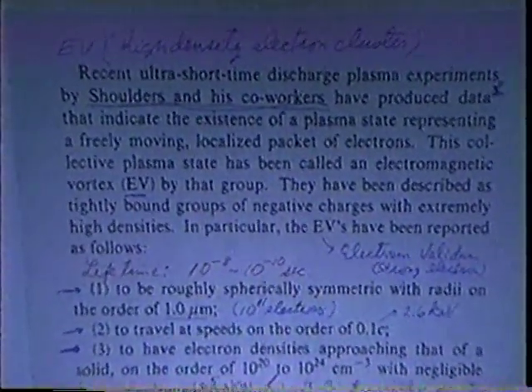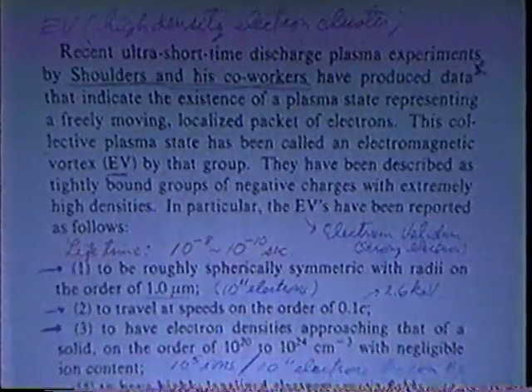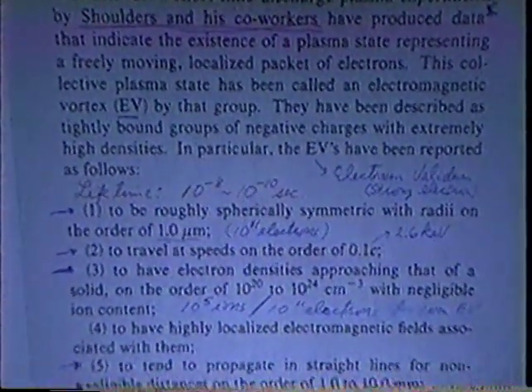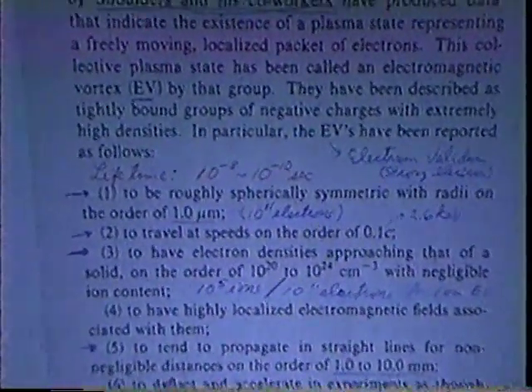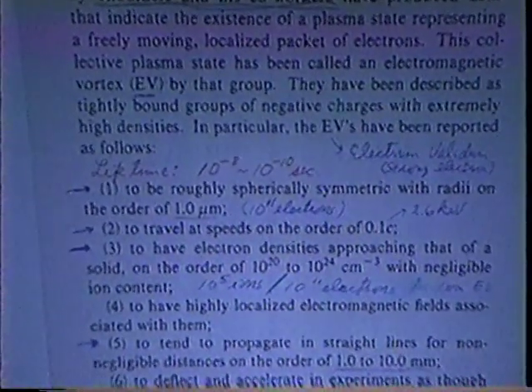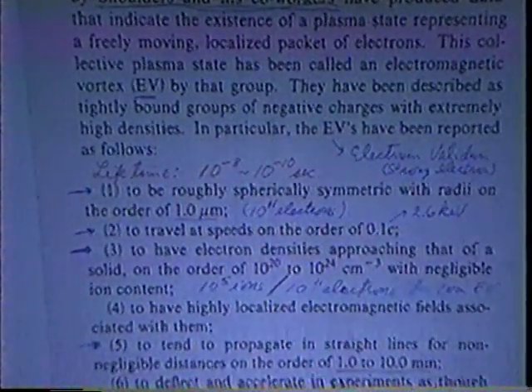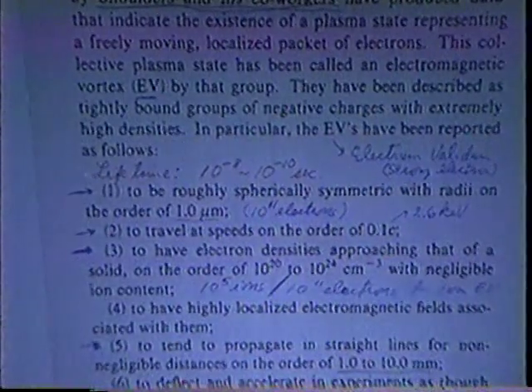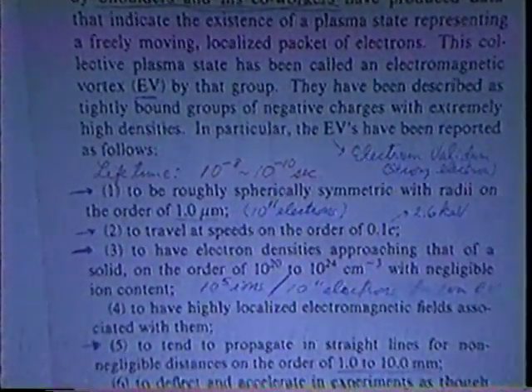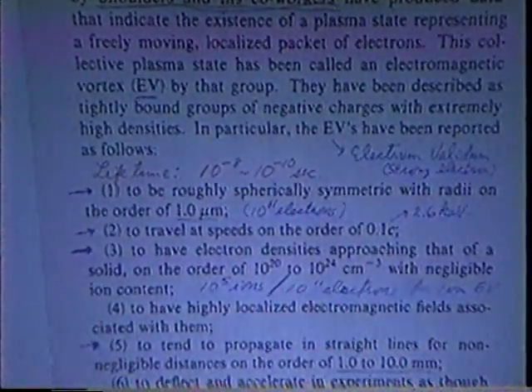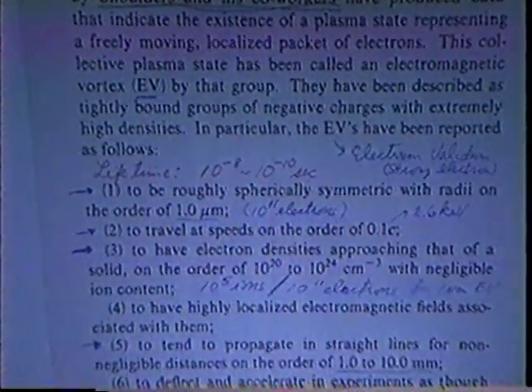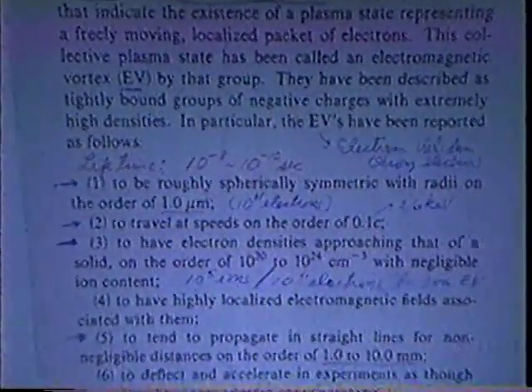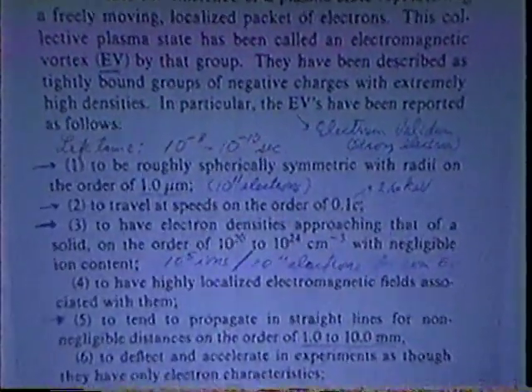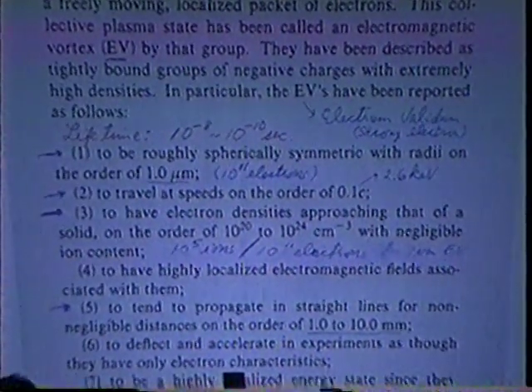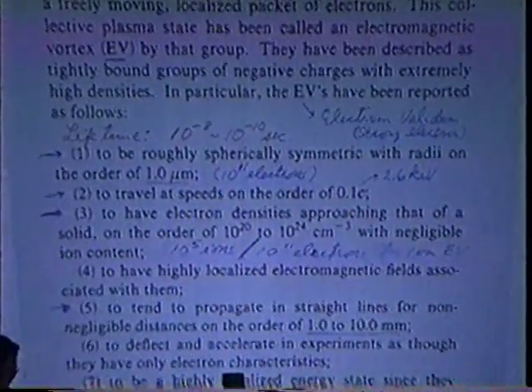In particular, if you have a high density electron cluster, that condition will be satisfied too. I will come to that next, but there is an observation by Ken Shoulders claiming that you can create a 1 micron size electron cluster which contains an Avogadro number per cubic centimeter. So that's about 10 to the 11 electrons. And the lifetime is of this order. And it may contain nuclei or ions to this order. And it can move this distance because the velocity is almost 0.1 of the velocity of light, and they apply an electric field or potential to create this by discharge experiment, which is 2.6 keV.